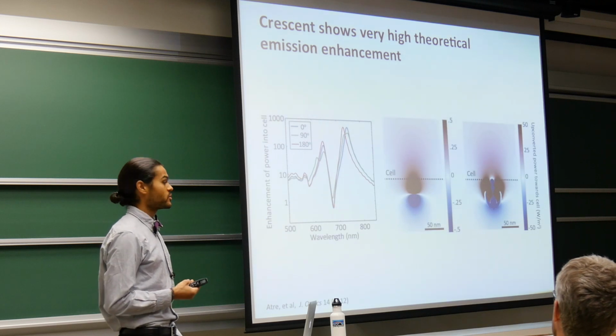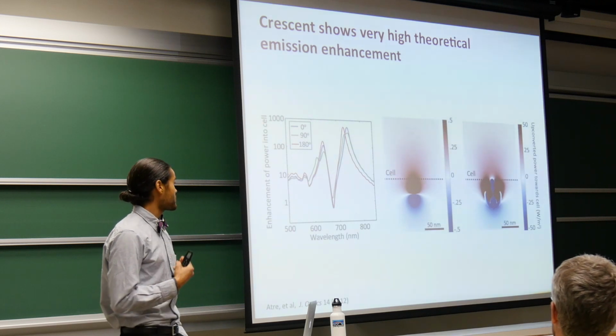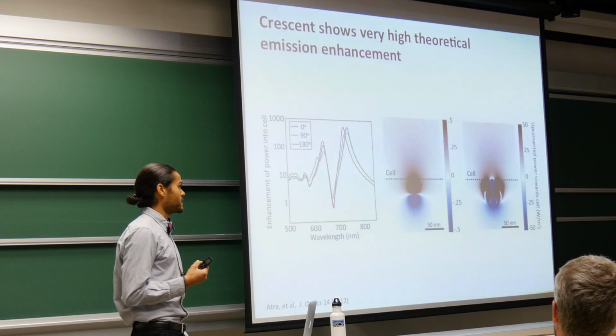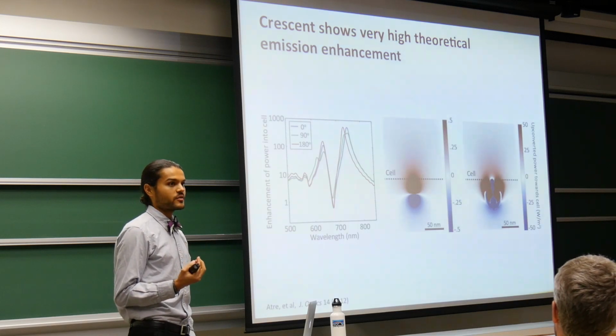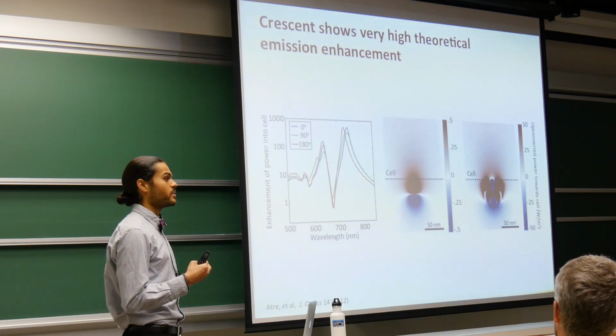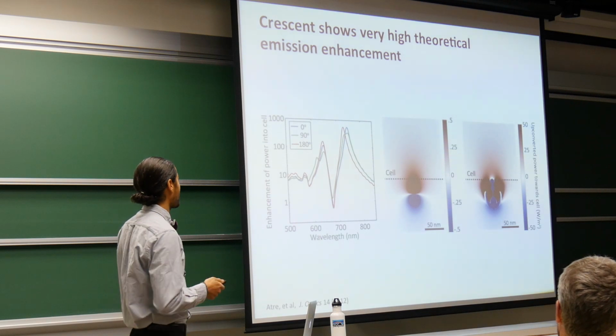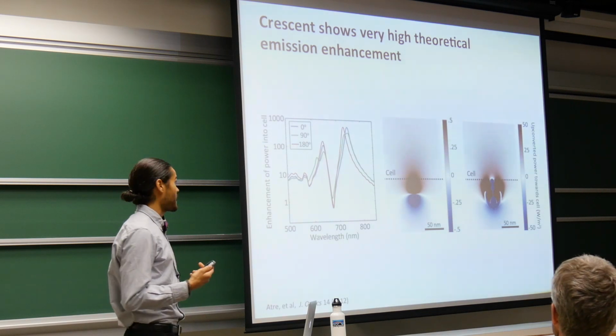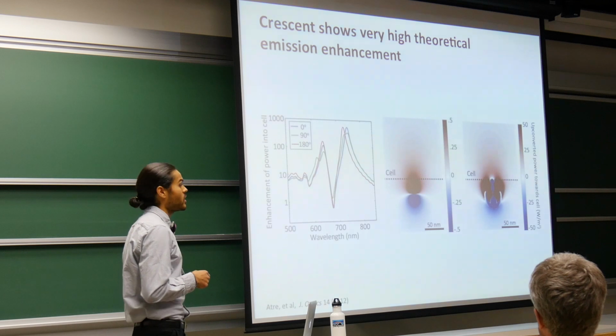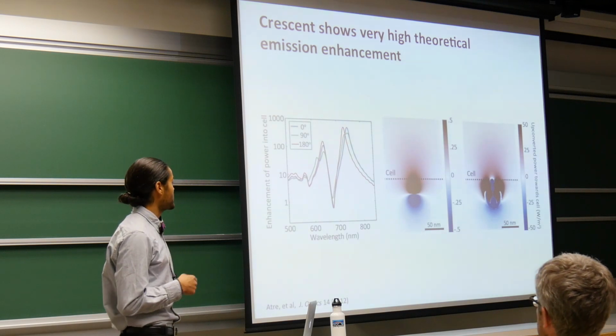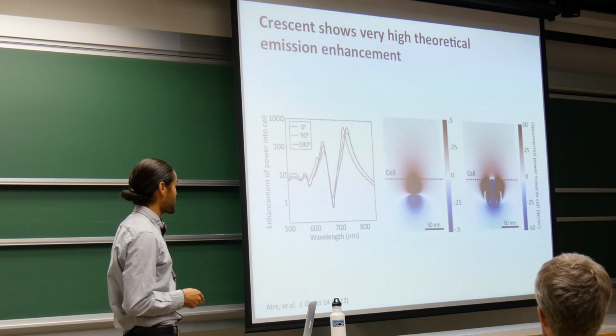Beyond absorption, we can also improve the emission. For this, we calculate the amount of light that's emitted by an upconverter, both in free space and when it's embedded in the crescent. When we do that, we find that the enhancement of this emitted power can be up to a factor of a few hundred, depending on which wavelength we're interested in.